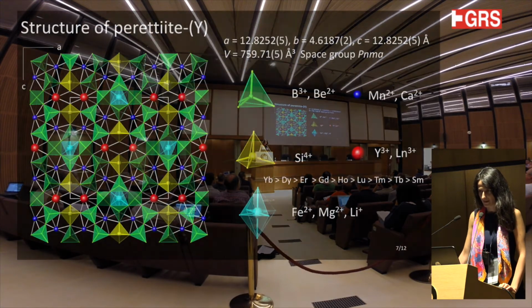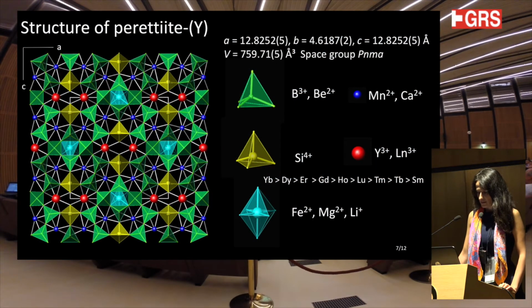So now, let's have a look at the structure of perettiite. Our structure refinement allowed us to describe perettiite as a borosilicate. In the picture, you can see the borosilicate layer. We have in green the boron tetrahedra that are to a minor degree substituted by beryllium. And then we have in yellow the silicon tetrahedra. They are arranged to form 4, 5, and 8 member rings.